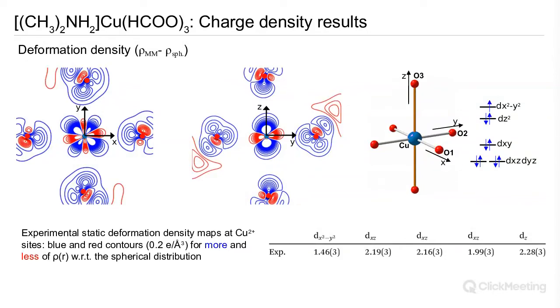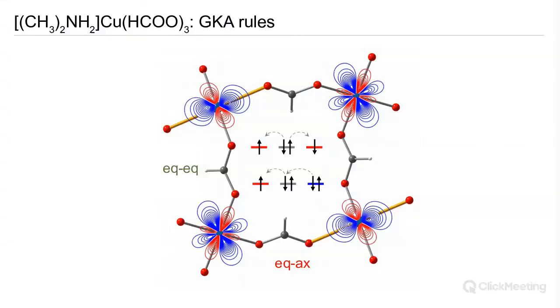So if we bring these 2 charge density results together, then what we essentially find is that the Goodenough-Kanamori-Anderson rules seem to work very well, despite the fact that we've replaced oxygen with formate. That is to say, we can treat every formate electronically the same, and what we see is strong antiferromagnetic exchange in the equatorial direction, where we have our half-occupied x squared minus y squared orbitals pointing towards each other through the formate, and we have very weak ferromagnetic exchange in the direction where we have the doubly occupied z squared minus r squared orbital pointing towards the formate here.